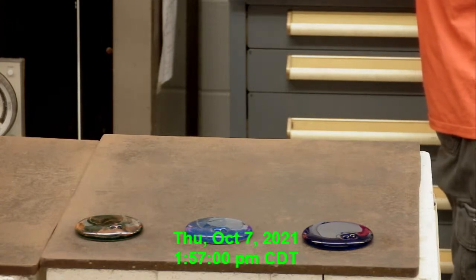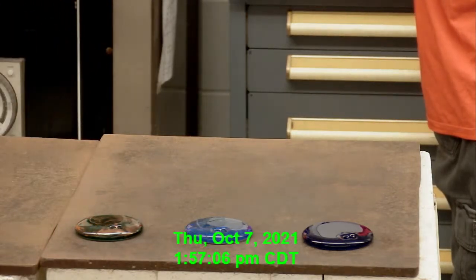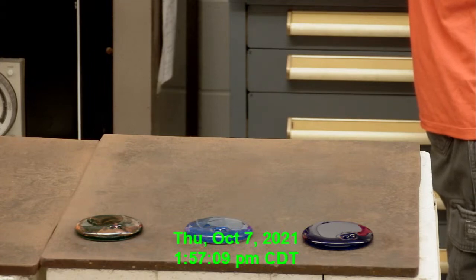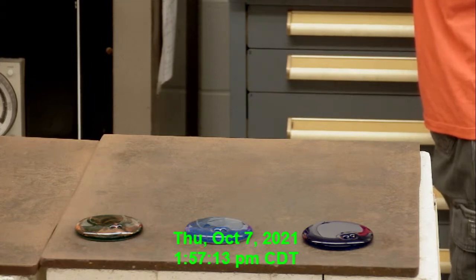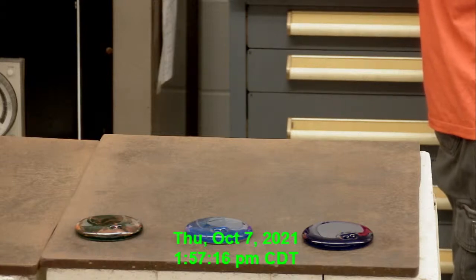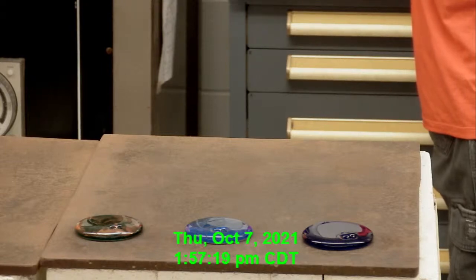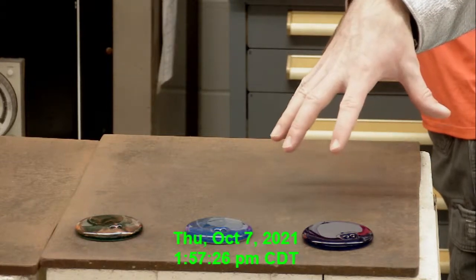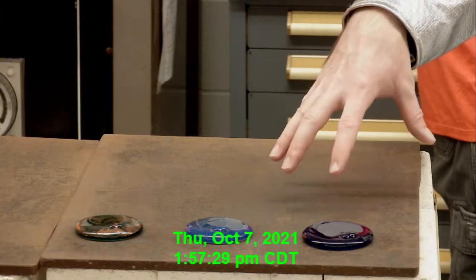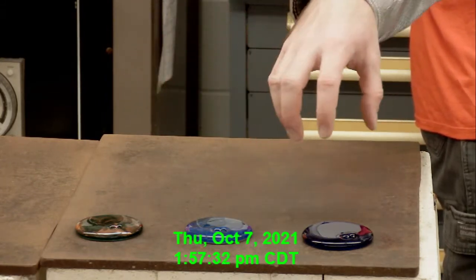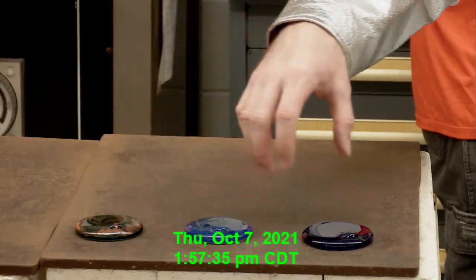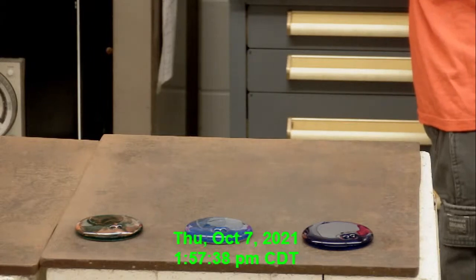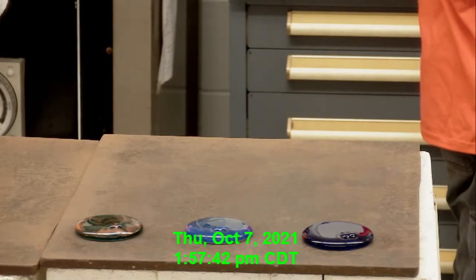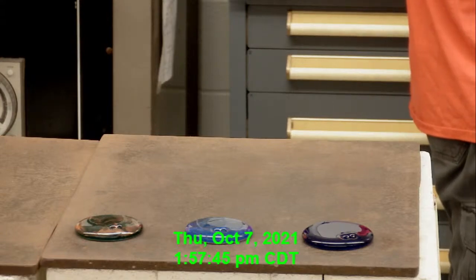Okay, so let's see what's next here. Next up we've got O1. That is a purified silica mason sand. Our first example of the borate. This is a half. The maximum for that ingredient is 10. We've got 5 grams of borate. The borate melts first and helps lower the overall melt point. So be watching for a lower viscosity glass and a larger disc as a result. So far these have been kind of similar. These are a little bit smaller than the first one, but this one I'm expecting to be a bit larger. So this also has sodium carbonate, calcium carbonate, standard pure stuff.